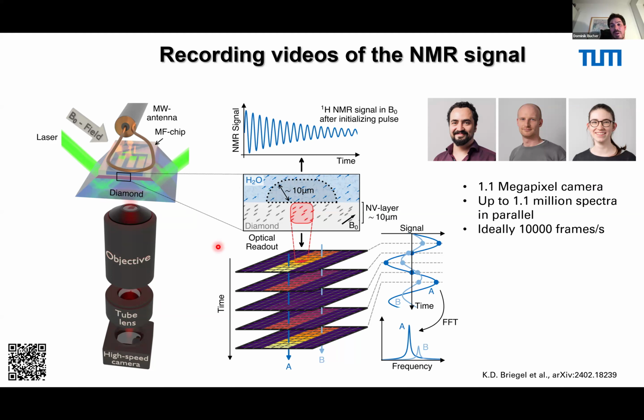And now see the big advantage of this technique. So first of all, the imaging happens in real space. So we do imaging in real space, which is very different from MRI. As we discussed before, you typically use gradients, similar to the diffusion experiments, to encode the information in space. So you apply gradients, and at the end you go to k-space, whereas here we can really do MRI in real space. And most importantly, in this case we had a 1.1 megapixel camera, so we get 1.1 million NMR spectra at the same time. And we see, of course, at the end, lots of data.